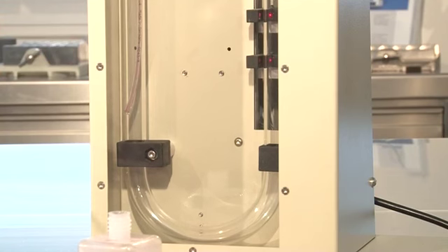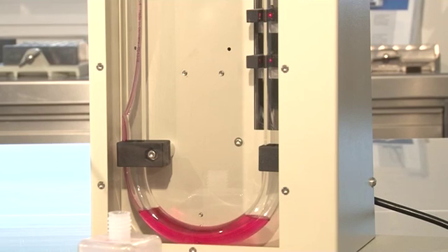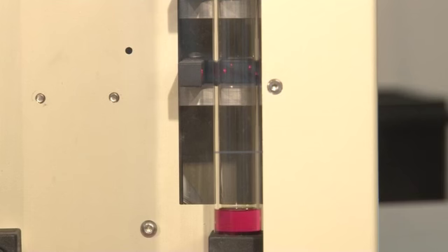Ensure that the tube can be seen in the U-tube so that the manometer liquid also reaches the tube. The manometer liquid is carefully filled into the U-tube. The U-tube must be clean and dry before being filled. The filling level gauge is reached.